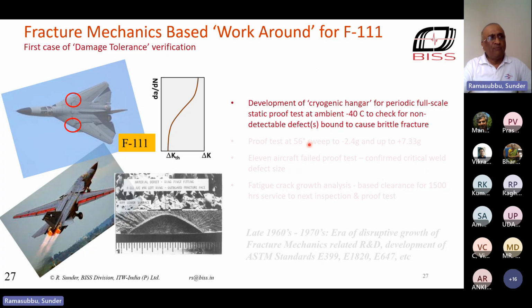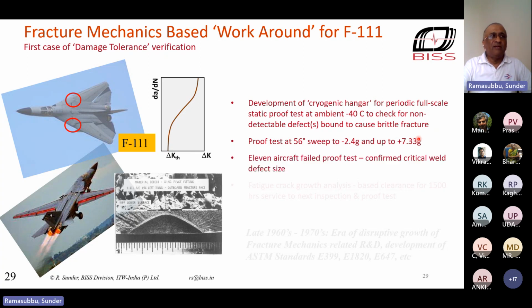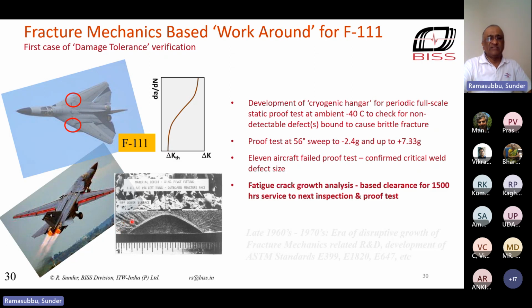And then they would apply a proof load. Keep the wing at 56 degree sweep, apply a load corresponding to minus 2.4 G and up to 7.3 G. 7.3 G means 7.3 times the flight weight of the aircraft in tension would be applied. And lo and behold, 11 of the aircraft actually failed the proof test. And this confirmed the criticality of the weld defect on the aircraft. So based on fatigue crack growth analysis for the first time in aeronautical experience, the aircraft was cleared for 1,500 hours of service till the next inspection and proof test.